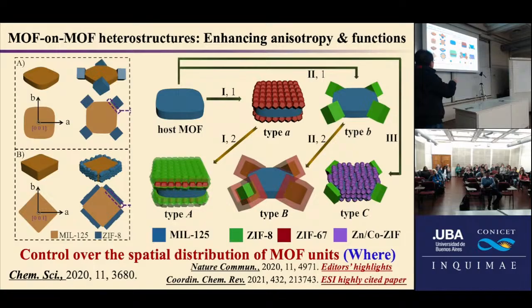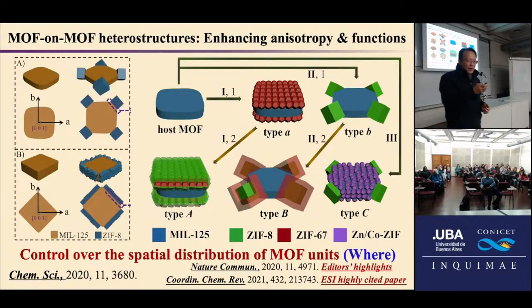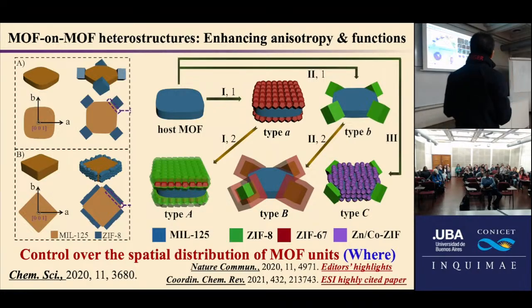Okay, so this is a work from 5 years ago. You can see we can use the host MOF and grow the guest MOF either on the corner, on the top and the bottom surface, and you can do this with 2 MOFs and 3 MOFs, all with well controlled morphology.